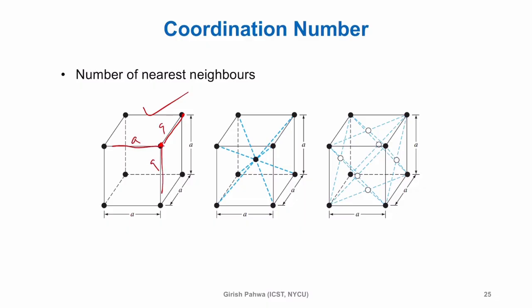A. So 3, right? Similarly, I can draw the same cube on the side. Here I can draw the same cube. So 4, right? And 5 if I draw a cube in the front, and if I draw a cube on the top, 6. So 6. Got it? If you don't get it, then go back to that whole cubic lattice picture. So there was this whole lattice I drew somewhere in the beginning. So you can very clearly see from there that there are 6 such points.